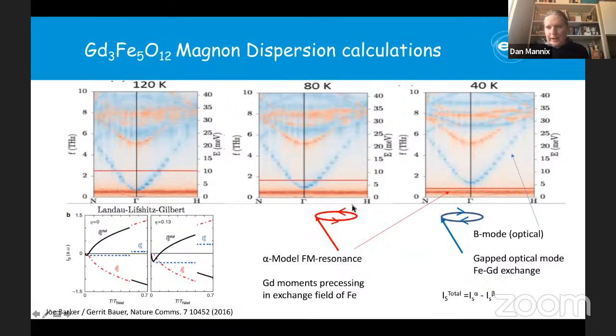In a pure ferromagnet, you only have one possible direction, one possible mode, but in antiferromagnets, you can have different modes that can be separated out because of these different exchanges between the sublattices. So the idea here is that these two modes pump differently. They do the spin pumping and generate a spin current in different ways. So the total spin current is given by the difference, and that will essentially switch over when you go to the compensation temperature. And because of the gadolinium and this effect going away at lower temperature, it will give a sign change in the spin current generated.